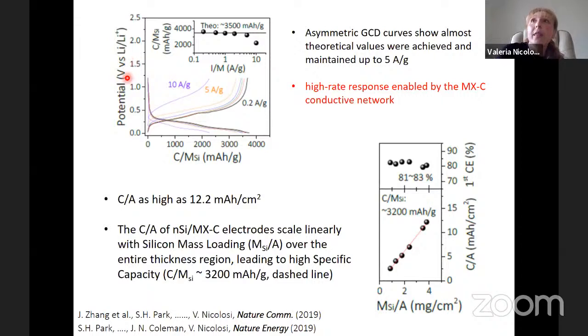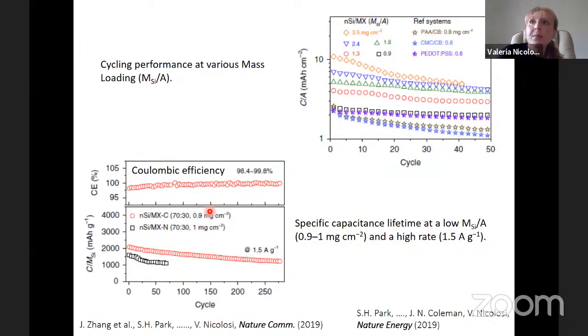So here is shown the response of these anodes as a function of the mass loading. And what is nice to see is that you get very nice asymmetric galvanostatic charge-discharge curves. Really, the theoretical limit is reached and maintained up to about 5 amps per gram. And this means that you have a very nice high rate response. If you look at the areal capacity that we could achieve, we could really achieve the theoretical limit, which is about 12 milliamp hours per square centimeter. So there was a state-of-the-art type of response. The cycling performance is something that should be improved, and we're working to improve it. We could cycle them hundreds of times, but still we want to get them longer.